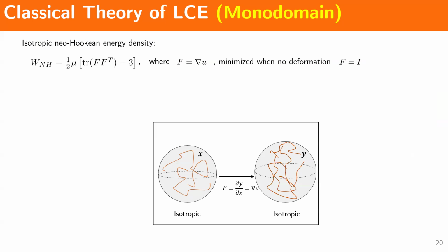Okay, so the classical theory of LCE for monodomain, the whole idea here is that the material essentially has a polymer backbone, right? So we're going to consider the simplest energy density form, which is the neo-Hookean energy density for our rubber materials, right? Now, the important thing here that I want to highlight is that this energy has exactly one ground state, one energy minimizing state. And so this is when the material is undeformed, right?